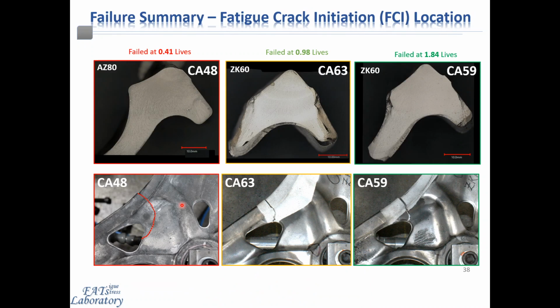Now, if we look at the final crack morphology for the three components that had this type of failure, we can see that they all look quite similar. However, the starting location and the branching direction is slightly different in the component on the left, as there was a surface defect which caused the initiation to be in that location.